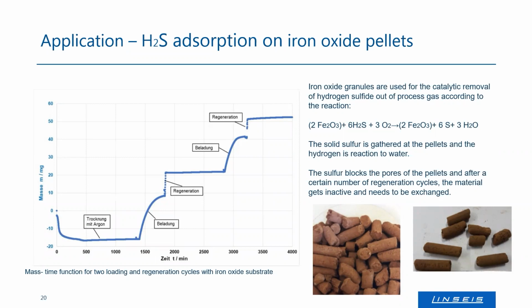And the main thing is you have these brown pellets you can see in the pictures. They are made mainly out of iron oxide, and they are used to get rid of hydrogen sulfide out of process gas by just bringing them into the gas stream. And then the hydrogen sulfide will react with the surface. It forms iron sulfide and some water, and then you can regenerate it by bringing in some oxygen. The oxygen reacts again with the iron sulfide. It releases some sulfur and forms iron oxide again, and it releases even more water and so on. And therefore you could get rid of the toxic hydrogen sulfide, and transform it into solid sulfur that you could even reuse, that is then gathered at the surface of these pellets.